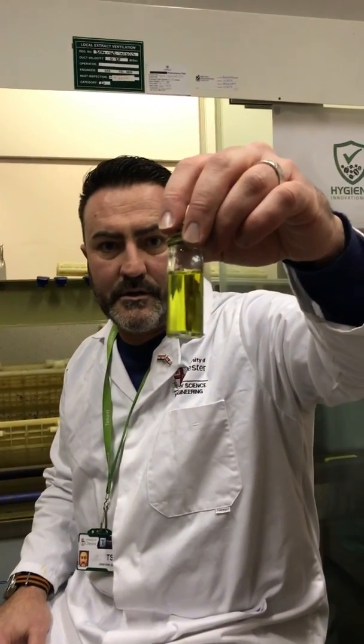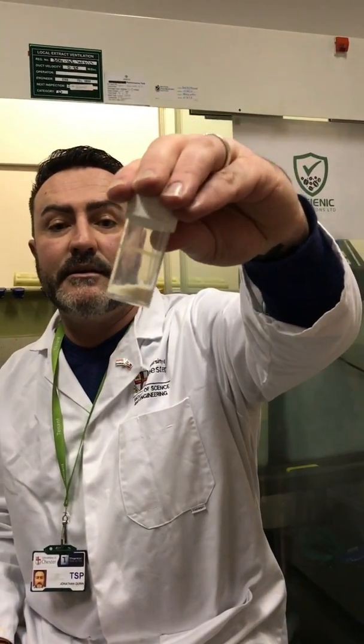So what is happening inside the tank? As the ultrasonics and the chemicals work together to dissolve the solder, the tin goes into the liquid. Then we supersaturate that liquid and pump it to a reactor, change the pH, and we end up with a solid tin, which can then go across to be processed with a tin smelter. On the copper, we can granulate this down further and recover it as pure copper. So again, you're enhancing the value of your metals all the way along.